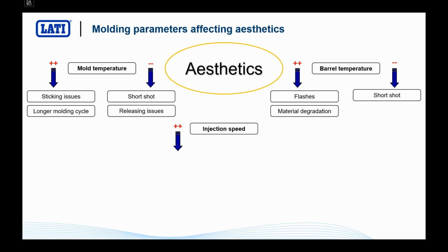If injection speed is too high, you can run the risk of having flashes or having overpacking or having burn marks. What does injection speed mean? It is the speed that you apply to your melt plastic to fill the cavity. When you apply a high speed, you are also applying very high shear stresses to the polymer, which can actually be destroyed by these stresses. It becomes more fluid, it can create some gases, you have a very bad mechanical performance of the part in itself, and you will have absolutely a poorly performing and a very bad looking part. So you want to stay away from too high injection speed.